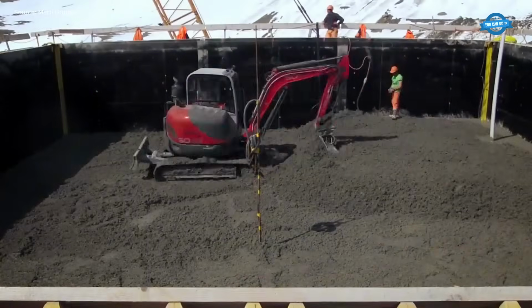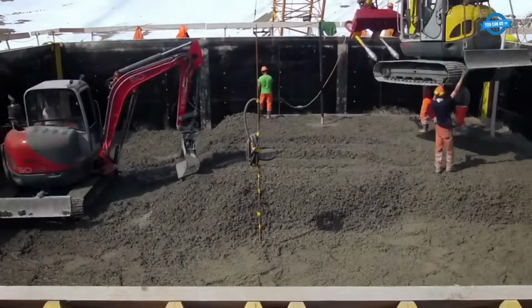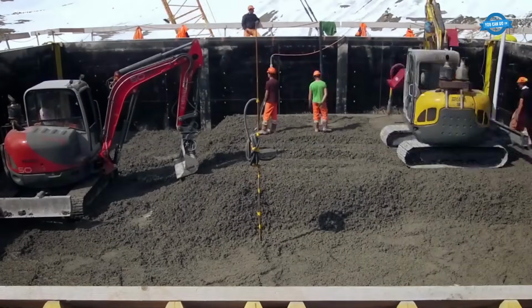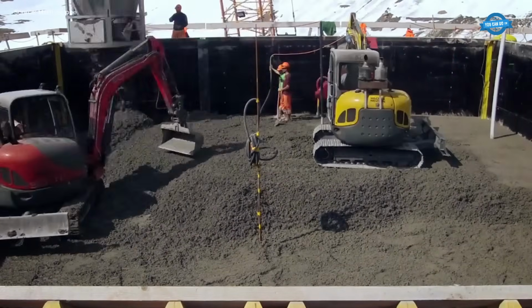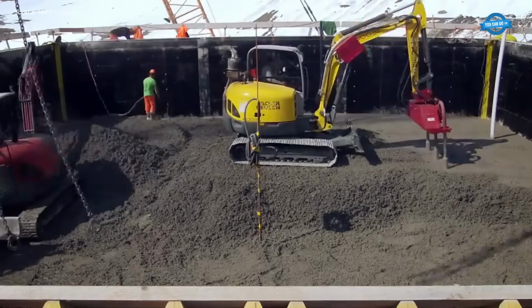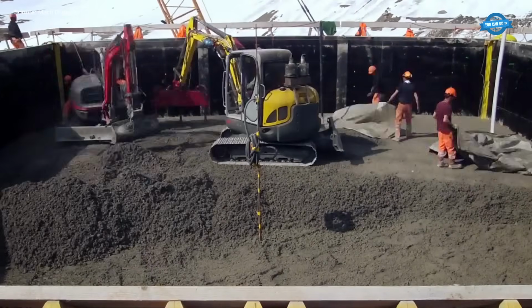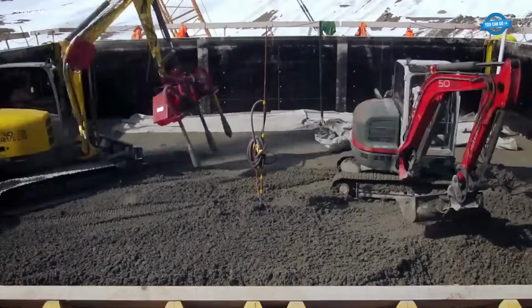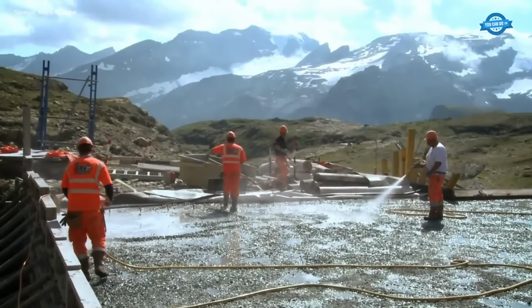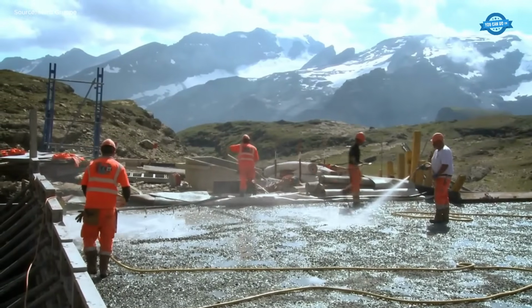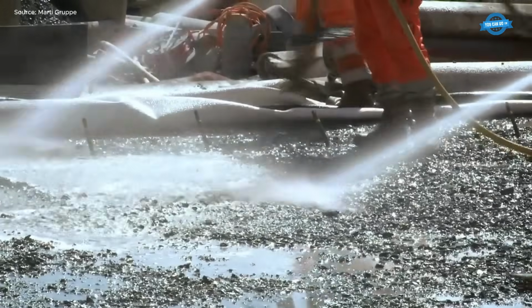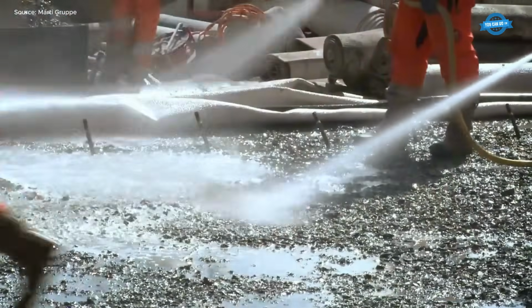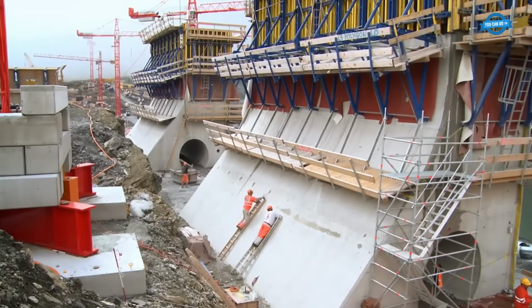The dam consists of 68 individual blocks, each 15 meters wide. Construction began with every second block to serve as formwork for the others. Blocks are built in 3-meter-high stages, with careful alignment of formwork and interlocking features between blocks. To prevent cracking, cooling pipes were installed in the large base stages to control the heat generated during concrete curing.